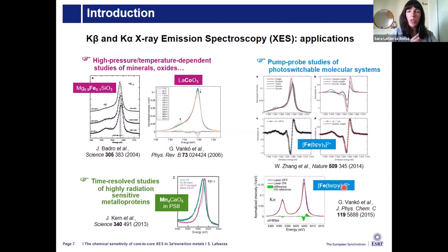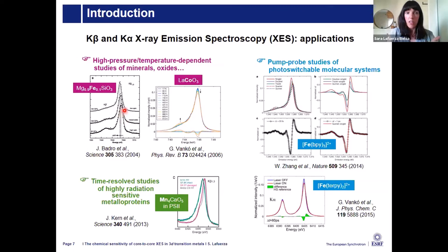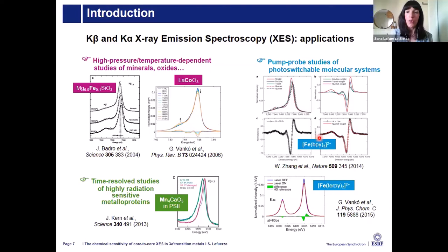A quick overview of some remarkable examples: both K-beta and K-alpha XES have been used for spin state determination studies, from material science to biochemistry. Because the relationship with spin is more direct in K-beta, traditionally it has been mainly used to follow spin state transitions — for example in high-pressure or temperature-dependent studies of minerals or oxides. XES is also very useful in time-resolved studies of radiation-sensitive proteins, since it doesn't need monochromatic X-rays and can be combined with diffraction to monitor sample degradation, as well as in pump-probe studies of transient states in photoswitchable molecular systems.